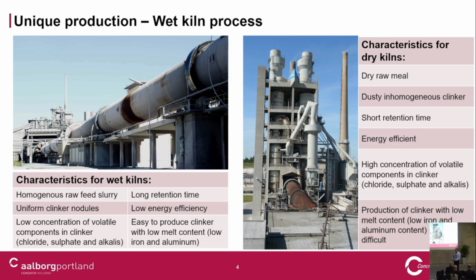That means that all the raw material particles are intimately mixed in suspension, so the feed into the kiln is more homogeneous than if we have powder raw meal fed into the kiln. In the wet kiln, we form very nice spherical nodules of uniform size, whereas in the dry kiln we have a much more dusty clinker coming out, meaning the sizes range from dust to bigger balls.